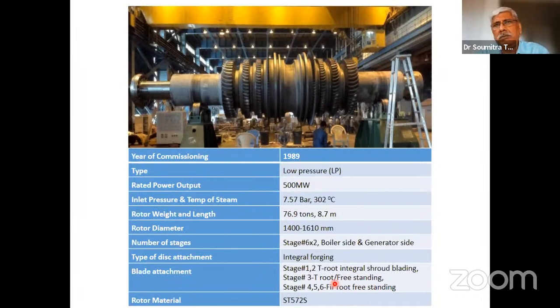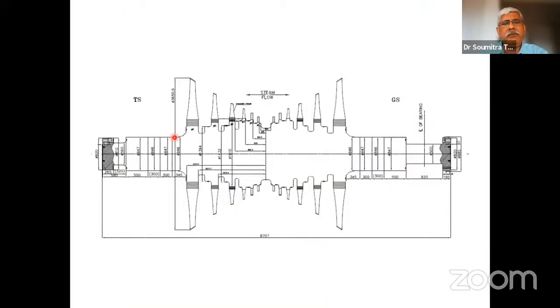This had worked for about 1 lakh plus hours with about 100 plus startups and shutdowns. But it was felt that a lot of life is still left in it. A rotor of this type can live for much longer. But because of this defect, what to do? And the problem is the defect was in the disc, which is part of the integral forging of the rotor. So this is the forging of the rotor. And these discs onto which the blades are fixed are integral to the rotor. And the defect was in this stage in the disc, the integral disc of the rotor forging.